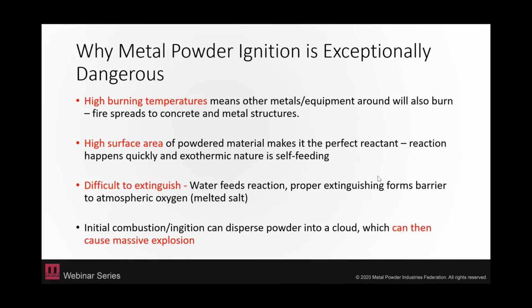So why metal powder ignition is exceptionally dangerous is because metals have high burning temperatures. So once you start a metal powder fire, not only will your powder be catching fire, but other things will be catching fire too. I believe the ignition temperature of aluminum powder is around 600 Celsius. So you can imagine a fire burning that hot, it's going to catch maybe the rest of your machine, your panels on fire, any plastic that's around, computers, concrete, metal structures in the building. It could just really get out of hand. The high surface area of powdered material makes it the perfect reactant, as we have been continuously emphasizing. That's the main thing to remember.